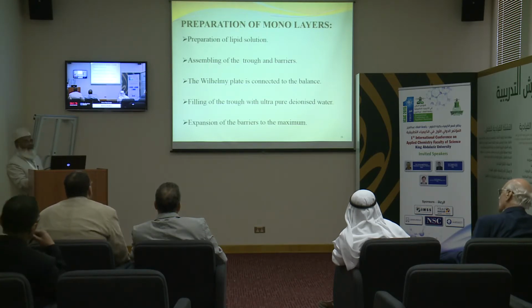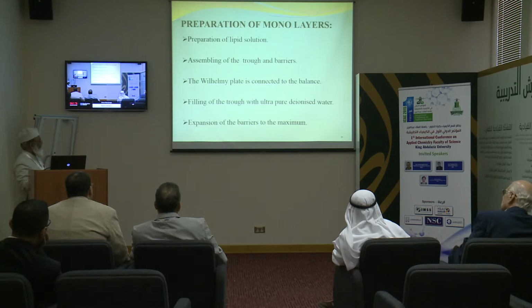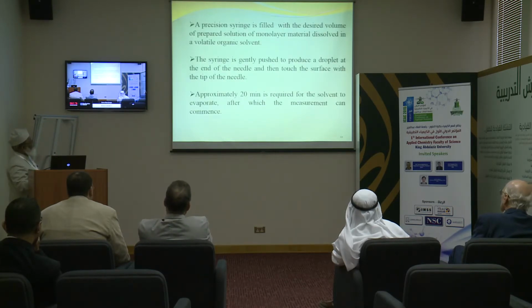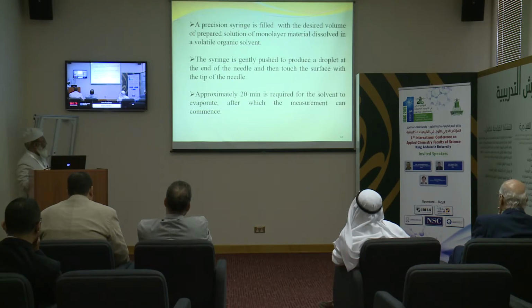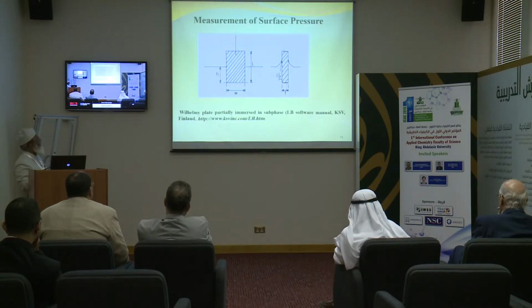A few steps regarding the preparation of monolayers: the preparation of lipid solution, assembling of the trough and barriers, the Wilhelmy plate, filling of the trough with ultrapure deionized water, and expansion of the barriers to the maximum. Then a precision syringe is filled with the desired volume of the prepared solution of monolayer material dissolved in a volatile organic solvent. The syringe is gently pushed to produce a droplet at the end of the needle and then touch the surface with the tip of the needle. Approximately 20 minutes is required for the solvent to evaporate, after which the measurement can be started.